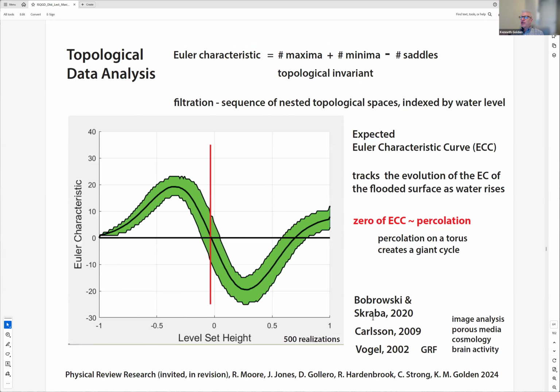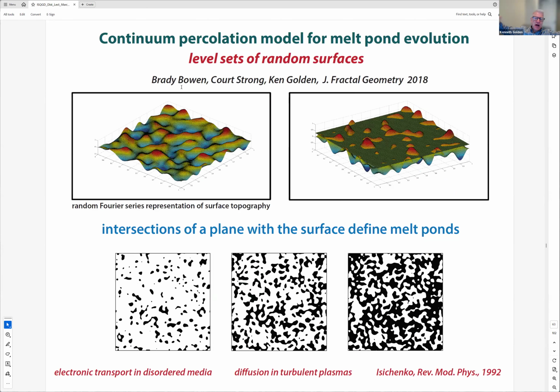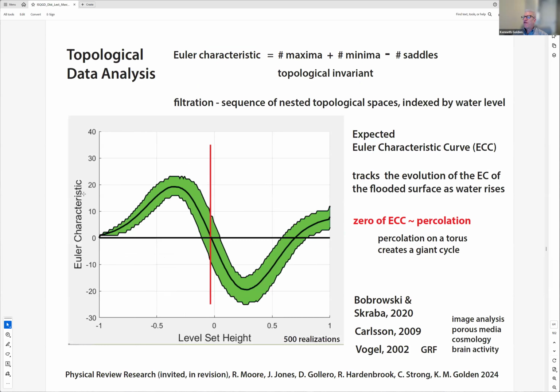And another interesting set of questions that this opened up was topological data analysis. In other words, as we move that plane up, we start with basically just hitting the minima. Then we start hitting minima and saddles of the topography, and then we finally hit maxima. And from that, we can measure the Euler characteristic curve as a function of the height of the plane, basically.